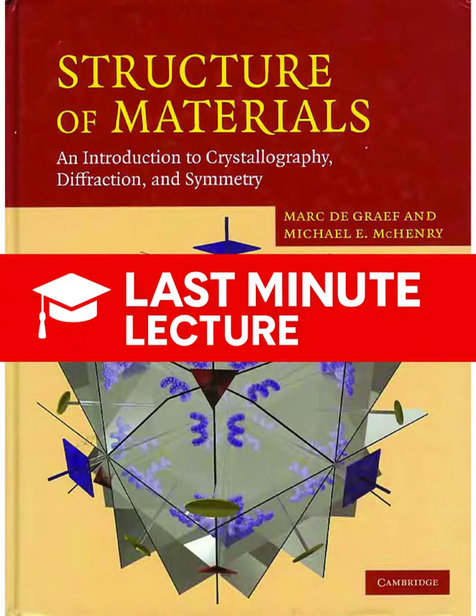It is. When you compare the visualization of directions and plane normals for the monoclinic crystal, the points do not overlap. The direction vector 111 and the plane normal vector 111 are plotted in two distinct locations on the Wulff net. This visual separation is the clearest possible evidence of the geometric complexity, and it proves why you need the metric tensor and the structure matrices to account for the distortions and decouplings in non-cubic systems. The cubic system is the exception, not the rule. The monoclinic projection shows us the true geometric difficulty in most real-world materials.